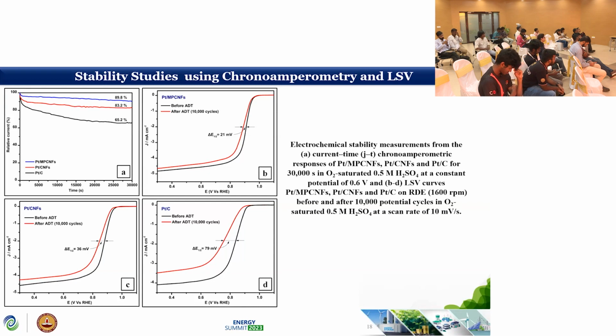And further, before and after the ADT test, after 10,000 cycles, we measured the LSV plots, and it was observed that there was a smaller shift for the Pt mesoporous carbon nanofibers. But if you see the commercial Pt/C, the shift was much higher. So it means that the degradation is much slower in the case of mesoporous carbon nanofibers.